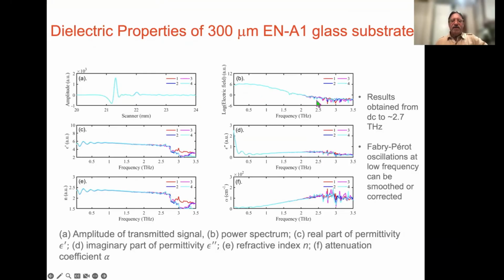So we can measure the electric field that propagates through the sample. We can analyze this data to extract either the complex dielectric function or whatever we want: the refractive index, the absorption coefficient, the loss tangent. Now, these oscillations are Fabry-Perot oscillations that we can correct for, actually, physically. So in these plots, they're there, but we know how to correct for that.